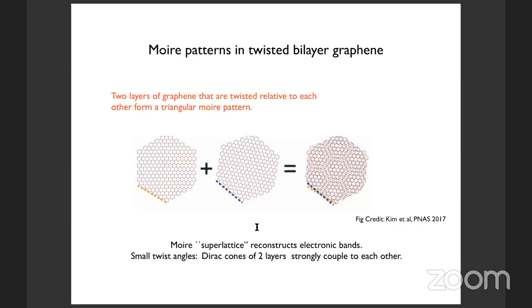Now, what we're interested in is the electronic properties of this structure, and this superlattice that's created by the Moiré potential strongly reconstructs the electronic bands, and if the twist angle is small, the Dirac cones of each of the 2 graphene layers couple strongly to each other, and you get a modified electronic structure. So I'm going to spend a few minutes talking about the old history of this subject. This will be very quick, and then we'll launch into the talk proper. Okay.